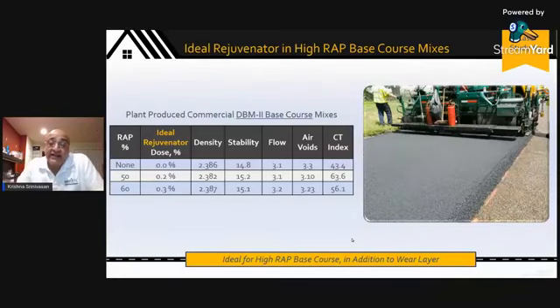This is a case that the previous several cases were for wear layer, or the top 2 inches, top 50 millimeter on which the tires ride. This is what's known as a base course. It is about 6 to 8 inches thick, about 100 to 150 millimeter thick. And these are examples of high RAP mixes used in the base course with and without rejuvenator.